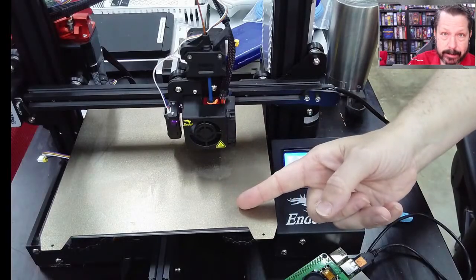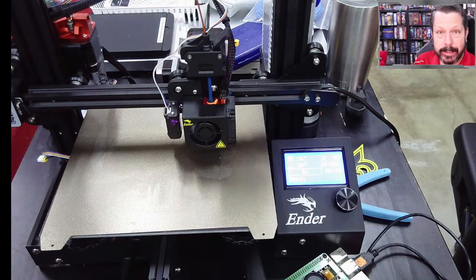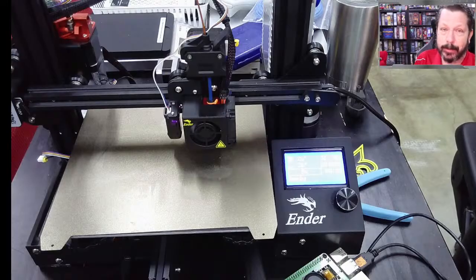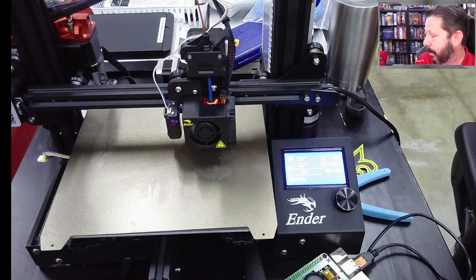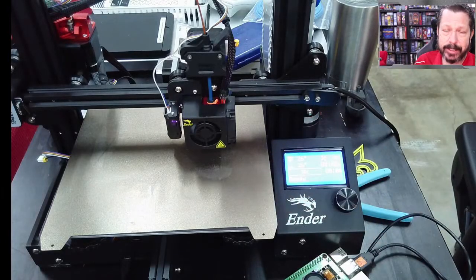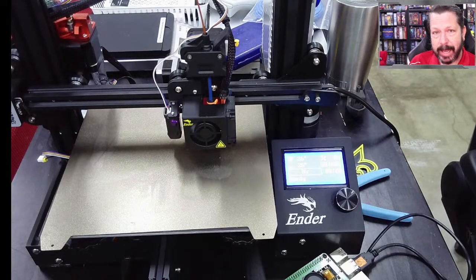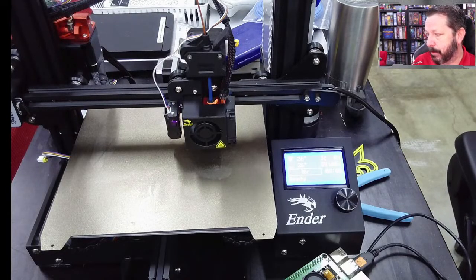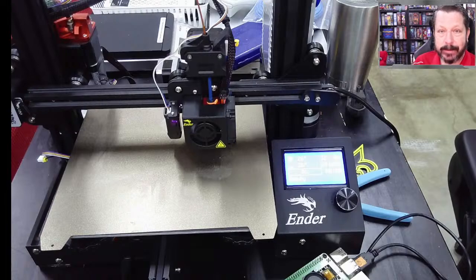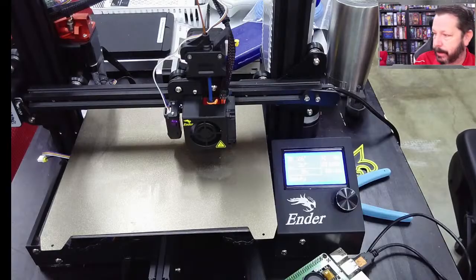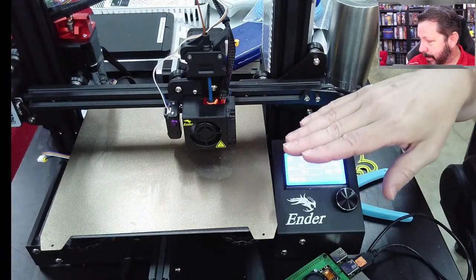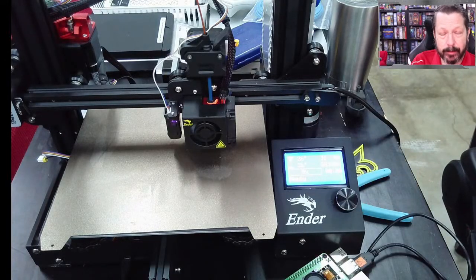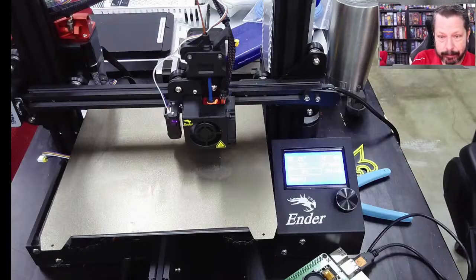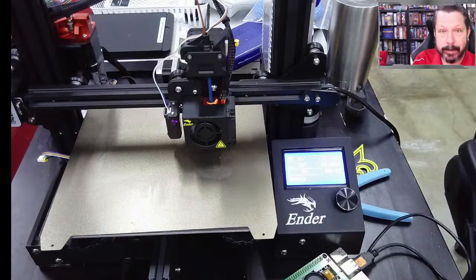You can put glue stick down. I don't normally like using glue stick, but it is useful as a release agent when you're printing TPU on flat glass or on some of the flat, smooth PEI sheets. Before I knew any better, I printed TPU on a flat sheet of glass that came from a picture frame. Back in the day, you just used whatever you could. The TPU stuck so well that when I went to remove it from the glass, it literally pulled chunks of glass off of the panel. So it can bond really well.